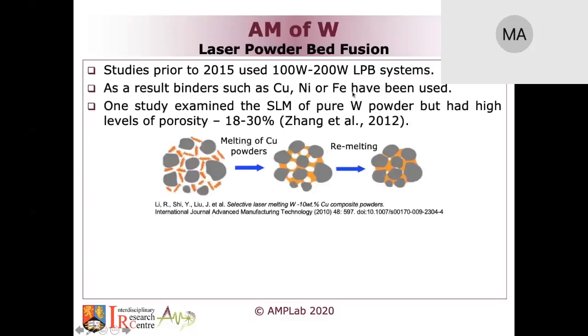And what you do is, when you melt these elements together, the nickel or copper or iron are going to melt, and they essentially act like a super glue, adhering to the tungsten particles, creating what we call in that case a tungsten heavy alloy. So you are basically just using those elements to get things to stick together.